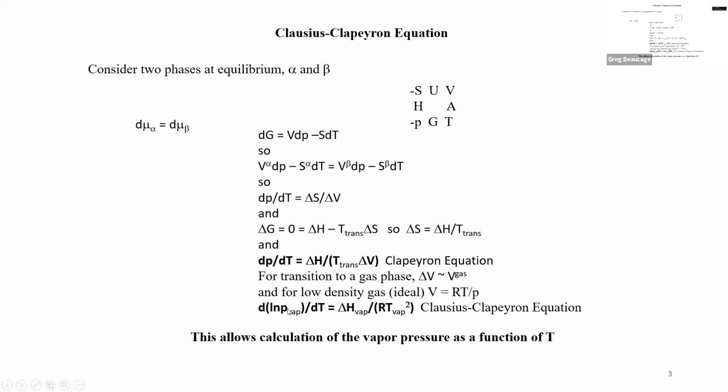So anyway, dP over P. Because you have a P here for the volume from the ideal gas, you get dP over P, which is d ln P. And then dT here, and because you have a T here and a T there, that becomes T squared. So dT over T squared is d(1/T), since the derivative of 1 over T is negative 1 over T squared. So basically, you can get the ln of P versus 1 over T, and then with the enthalpy here, you can get the Arrhenius function by this weird route. We did that in the 1800s.